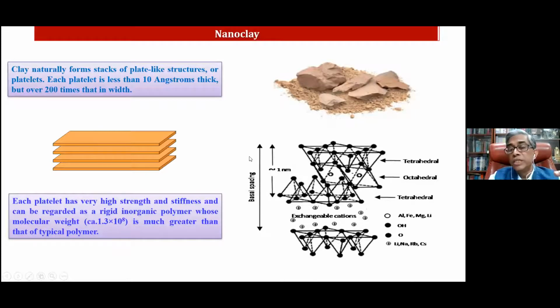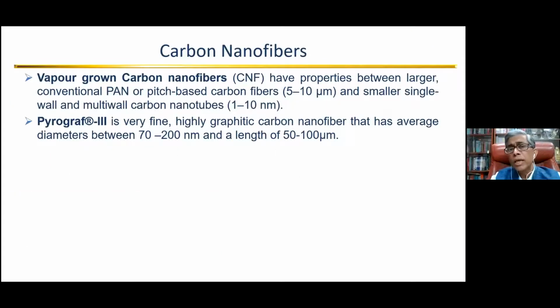And they have a D spacing, which is called a basal spacing. This gap, and what cation is inside these layers, is very important. And we can play with it, with our polymer and all that, to see how this polymer can go into that.